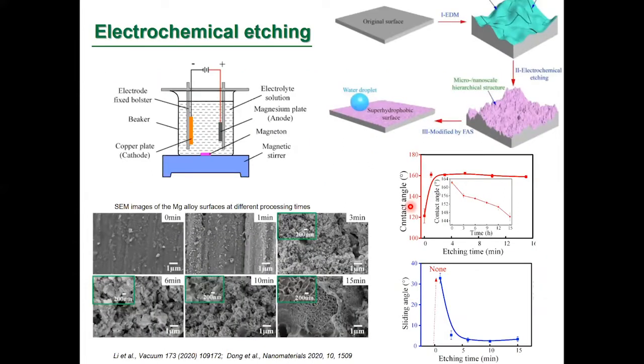So electrochemical etching, we know, is a simple process used to etch the surface. The electrochemical etching, especially for some metals like magnesium or a metallic substrate, can make nano and micro scale surface structuring. And with the suitable modification, depending upon the etching time, the contact angle and sliding angle vary, and that further depends upon the surface morphology resulting from the etching process.